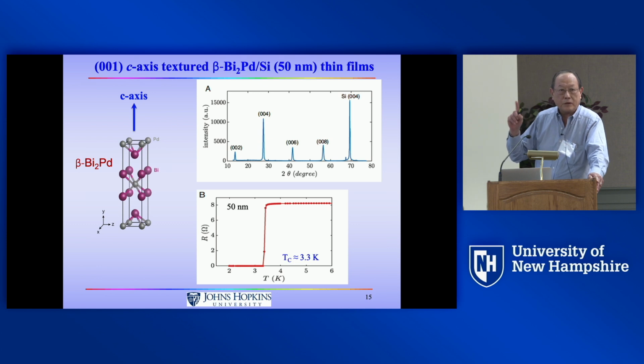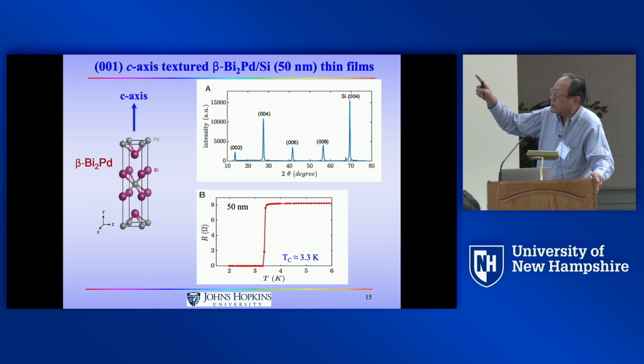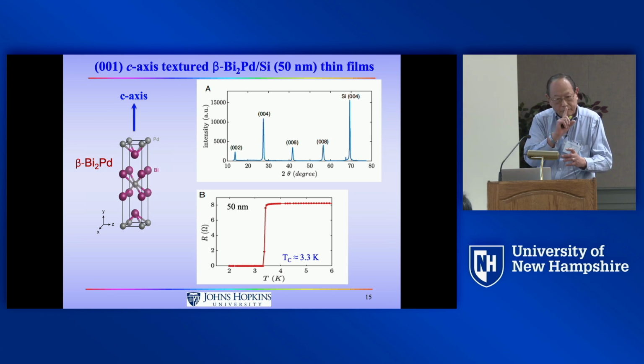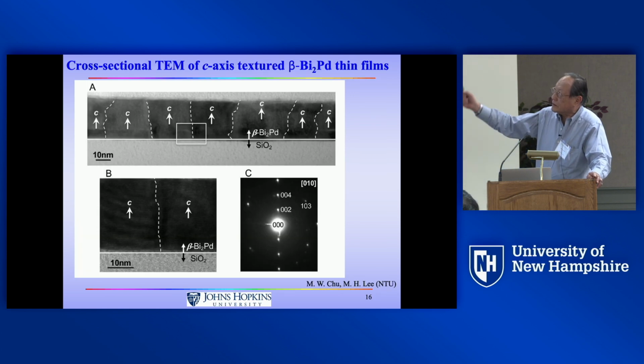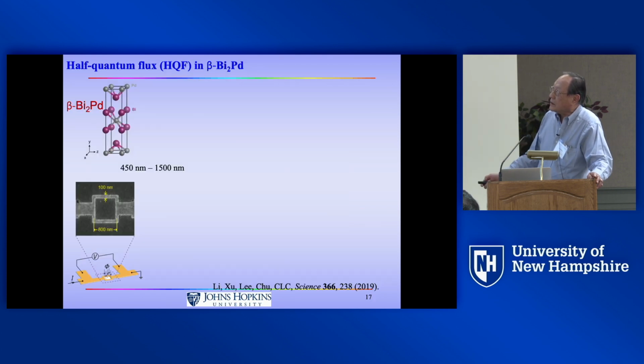So we make a thin film because we need a patterned ring. This is a polycrystalline ring. The polycrystalline material is all c-axis oriented, so it's polycrystalline, but every grain is c-axis. And the Tc is respectable, 3.3. This is the TEM cross-section showing that it's c-axis oriented. And you make a ring.